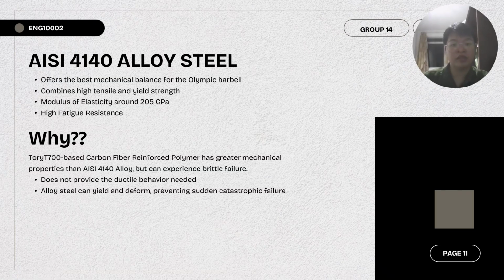Out of the metal, ceramic composite, and carbon fiber reinforced polymer options, the best material for an Olympic barbell is AISI 4140 alloy steel. This material offers the most effective mechanical balance. It provides high tensile and yield strength with a modulus of elasticity of about 205 gigapascals. It also has strong fatigue resistance, which is important for repeated loading in lifting. Even though Toray T700-based carbon fiber reinforced polymer has greater mechanical properties, it can experience brittle failure. It does not give the ductile behavior needed for a safe barbell. AISI 4140 alloy steel can yield and deform when overloaded, which helps prevent sudden catastrophic failure. For these reasons, AISI 4140 alloy steel is the best and most reliable choice among the three material classes.